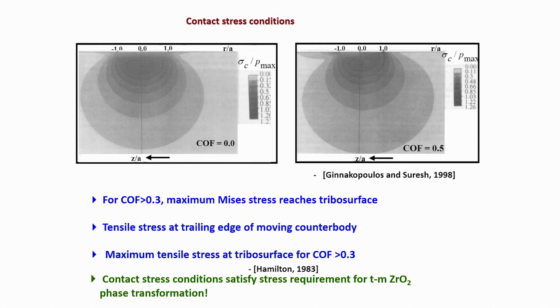And from there one can do some calculations. Just to show you, this is one of the papers, I think it was published in Acta Materialia in 1998, and the group from MIT, Subra Suresh and his group, has shown this contact stress region. At the frictional surfaces, with coefficient of friction 0.5, the high contact stress region is shifted towards the tribological surfaces, and tensile stress is always experienced at the trailing edge of the moving boundary, and maximum tensile stress at the tribo surface is reached when the coefficient of friction is 0.3. Therefore, you have a favorable contact stress environment which can trigger the microcracking in this particular case of zirconia.